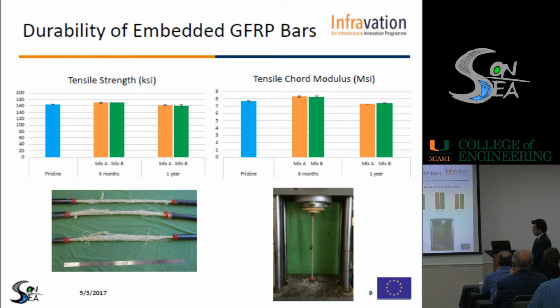This is after 6 months. So after 6 months, we went there, we took out the beam from the chamber, we extracted the bar, and then we tested it. So as you can see, actually the tensile strength went up after 6 months. So we had a higher tensile strength after 6 months, and also the chord modulus. So basically the tensile properties of our rebar improved over time. So that could be related to the cross linking of your GFRP bar.